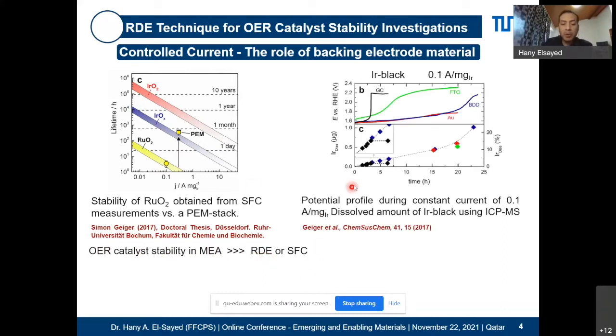The same group also came up with an explanation for this phenomenon, and they basically showed that this is mostly due to the passivation of the backing electrode. The backing electrode is a substrate on which the catalyst layer is sitting. They recommended not using glassy carbon, of course, and we all know this: if we're going to go to high potential, we should not. But they recommend using, for example, gold or boron doped diamond. Why? Because it just takes much longer for the catalyst to collapse.